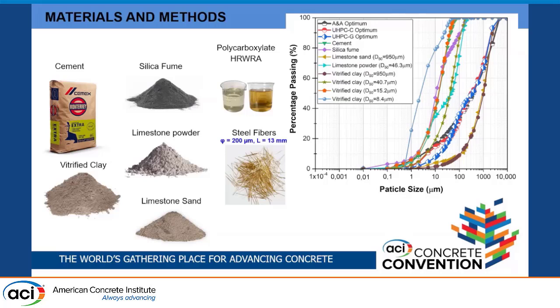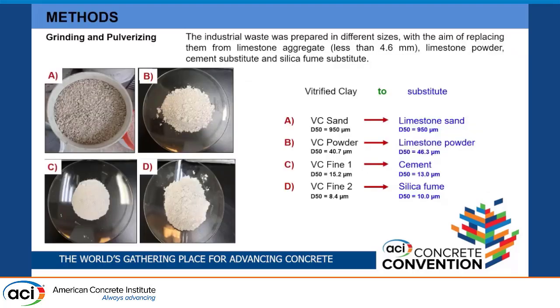Those are the particle size distributions of the different granular materials that we use. You can see the average particle size of the materials, the limestone sand, the limestone powder, and we prepared the vitrified clay in 4 different particle size distributions to substitute cement, silica fume, the limestone powder, and the limestone sand. Those are the 4 materials that we obtain by grinding and pulverization, and you can see the particle size distributions of the materials.